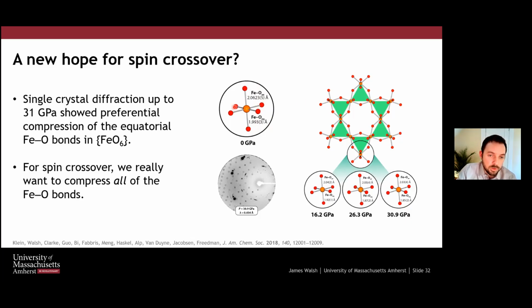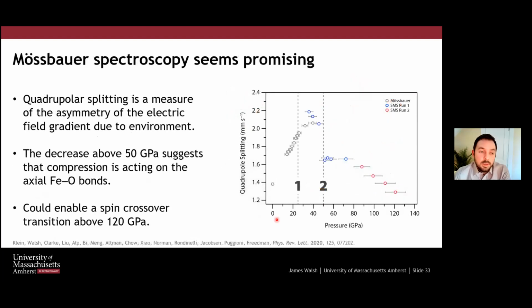So these 4 oxygens, those bond lengths reduce much more than the axial bond length, which goes from 2.06 to 2.03. If this is too small, we're going from 1.99 down to 1.85. So significantly more compression in the equatorial direction. But what we really want to do is compress all of those at the same time to increase the crystal field splitting. This is the last slide.